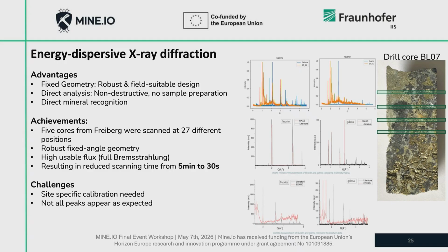We scanned several cores from Freiberg at different positions, using the fixed angle geometry and the high usable flux. With the energy dispersive approach, we could reduce the scan time from 5 minutes to about 30 seconds. But there are also some challenges. We found out that we would need a site-specific calibration, and because of the orientation challenges, not all peaks that help to identify the actual minerals appear as expected. So there's still some work to do in this case.